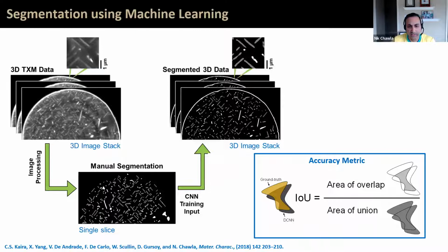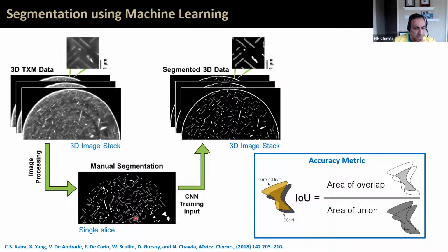transmission X-ray microscopy data. This is a stack of images. And then we manually segment some of those, okay? Maybe 100 of these images we can do with manual segmentation. This set of images is then used as training for the machine learning algorithm. So we actually incorporate actual grayscale images and segmented images all together, and we put this into the training part of the machine learning algorithm.